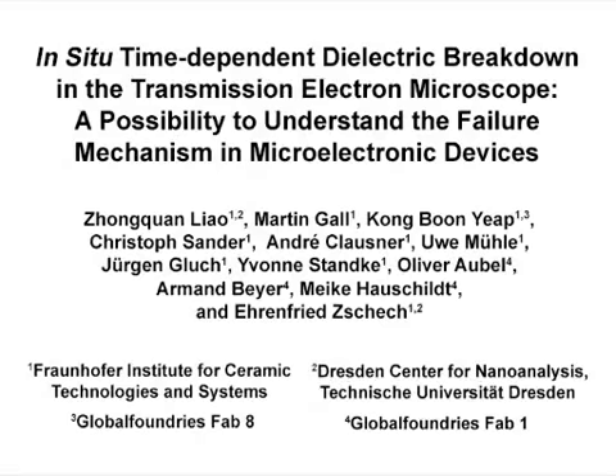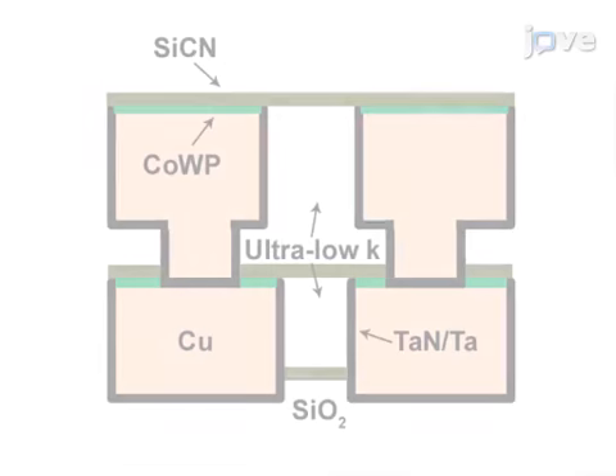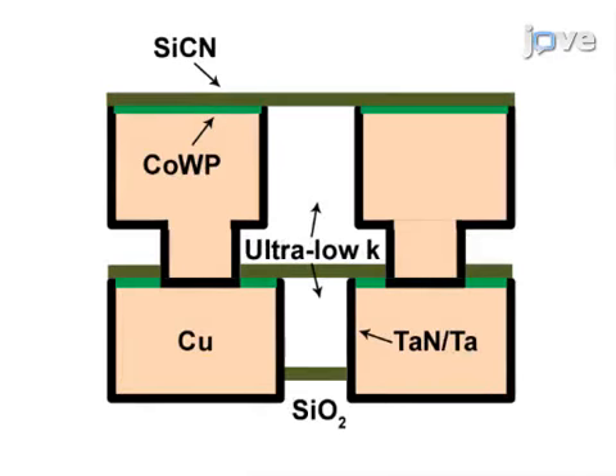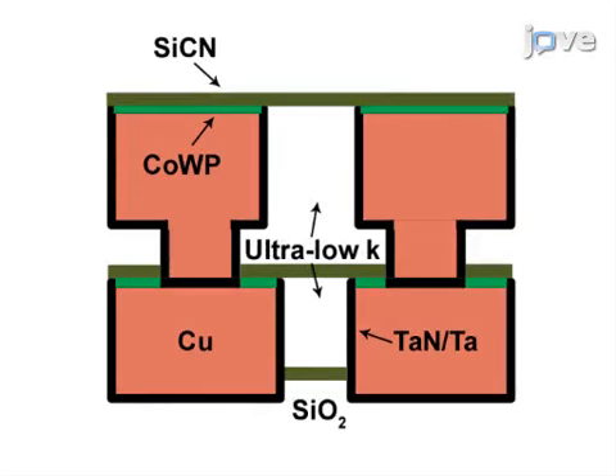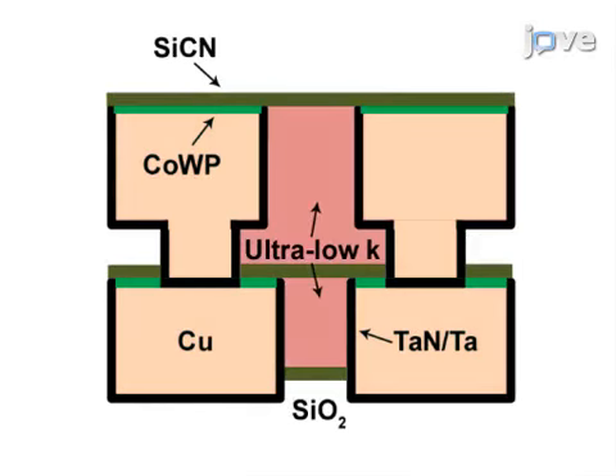The overall goal of the following experiment is to improve the procedure used to study the time-dependent dielectric breakdown failure mechanisms and degradation kinetics in copper ultra-low-K interconnect stacks. This is achieved by designing and fabricating a dedicated tip-to-tip structure consisting of fully encapsulated copper interconnects and insulated by an ultra-low-K material inside a full wafer.